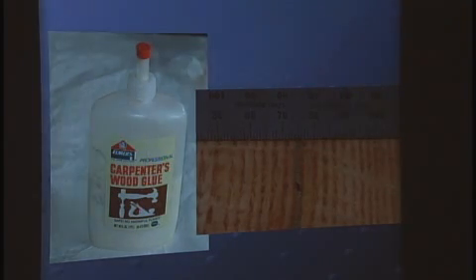There's also the issue of the impending brittleness and discoloration of the PVA emulsion. Our friend and colleague Steve Koob argues, and I think persuasively, that it's due to the virulent nature of many of the industrial surfactants that are used in the preparation of PVA and other emulsions. I would assume that if we wanted to make our own, we could. And I do, on occasion, make my own emulsions with acrylics and other resinous materials.